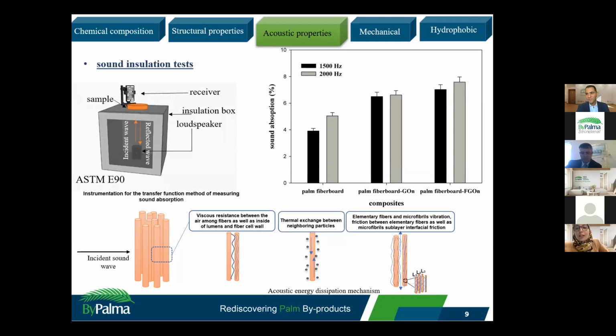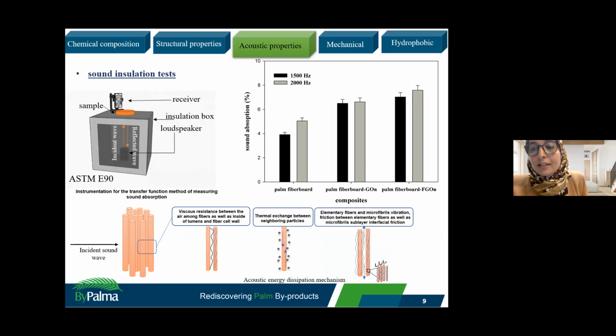So as you see, the results show that the presence of the graphene nanosheet will increase the sound absorption coefficient, which is due to the presence of voids between particles and fiber. At high frequency, the fiberboard has a slightly superior acoustic absorption ability compared to low frequencies. The results for these 3 composites confirm that the acoustic absorption mechanism is very complicated due to the complex microstructure of natural fiber.